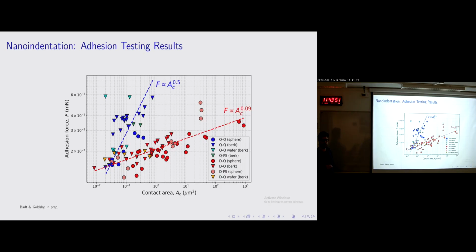Triangles are the sharp pyramid into the flat. The circles are the spheres into the flat surface. And we see the adhesion force versus the contact area at the point of adhesion. So the force is really loosely dependent on the contact area for the inert diamond-quartz contact, but follows an interesting trend where the force is proportional to the square root of the contact area for the quartz-quartz contacts. You also see that obviously quartz-quartz adhesion is higher than the inert diamond-quartz. What's going on here?